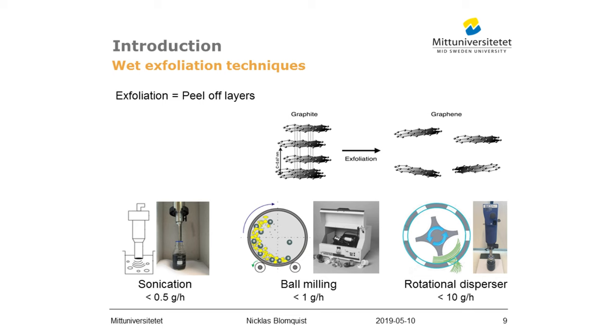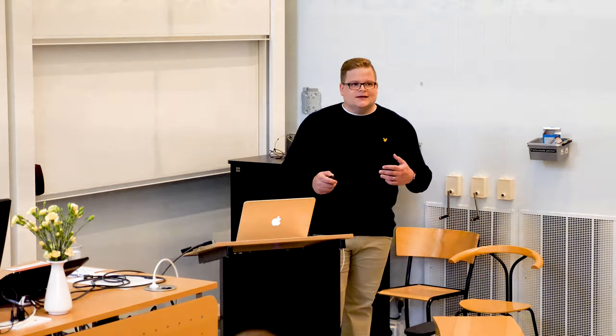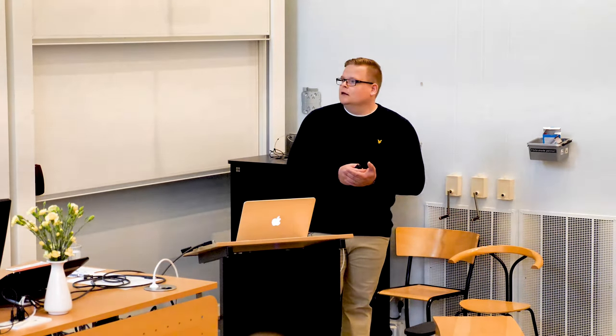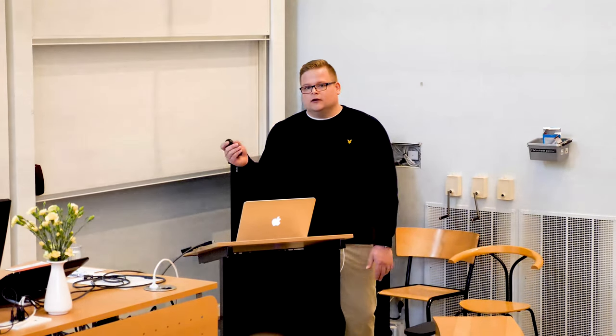Different approaches to exfoliation use different exfoliation techniques, but shear force is preferred to gently peel off these graphene layers from the graphite structure. But unfortunately, both edge collision and random collision also occur in these approaches, which can crack the flakes to smaller fragments.